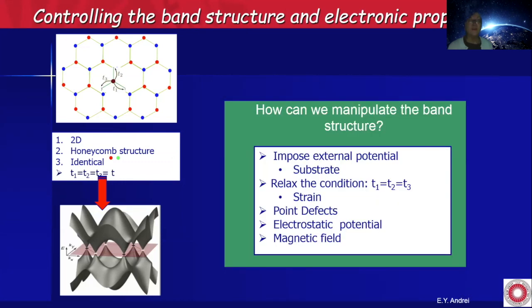So basically, we now have an idea of recipes of how to change the band structure. You can impose an external potential, for example, by putting your graphene on a substrate or any other two-dimensional material. You can impose strain, so you relax the condition of equal hopping parameter by using strain. Of course, there are other ways of doing it: introducing point defects by plucking out atoms from the lattice, applying electrostatic potential, magnetic field. I will focus on the first two.